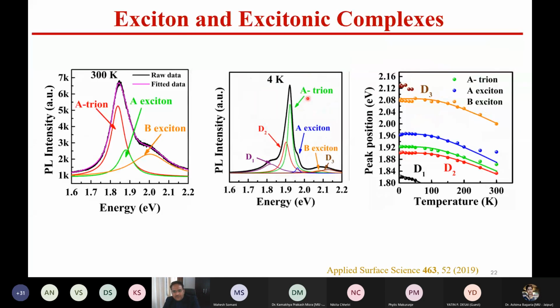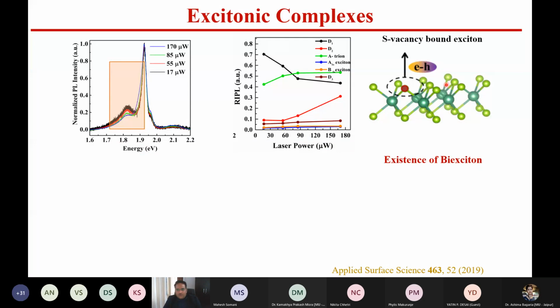So this is the A minus trion, this is the A exciton, this is the B exciton. So what are these D1, D2 and D3? These are the peaks which come at low temperature, and certain peaks exist up to room temperature also. The first thing one can do is a power dependence photoluminescence spectroscopy.